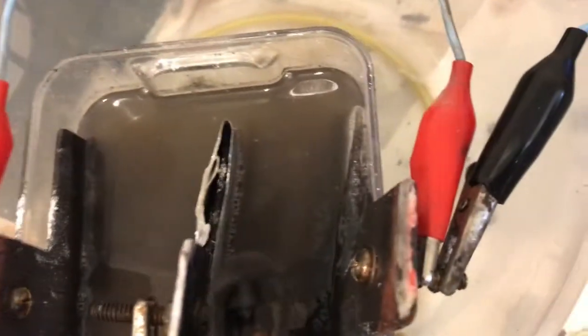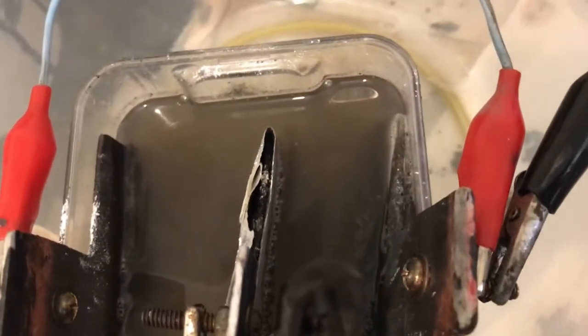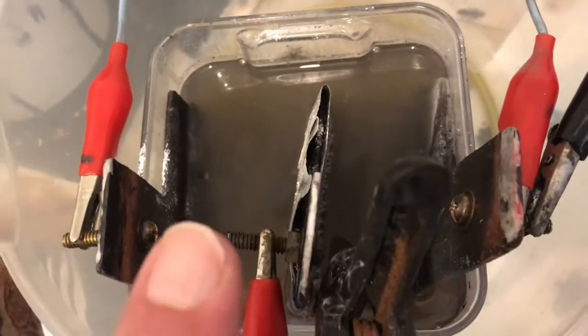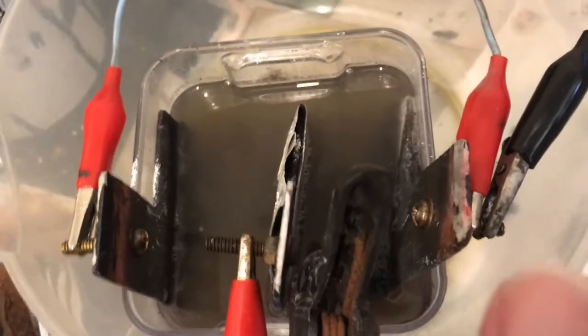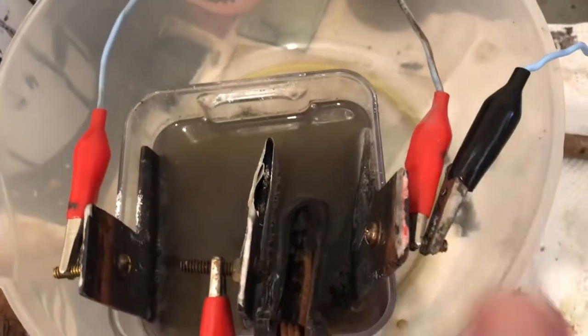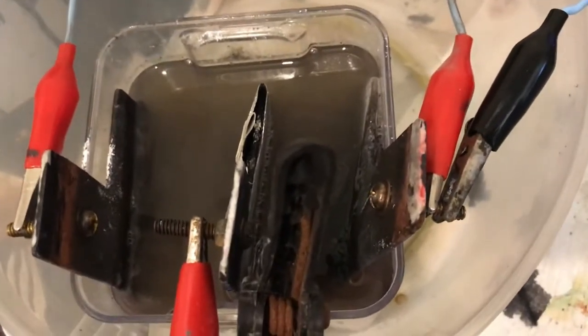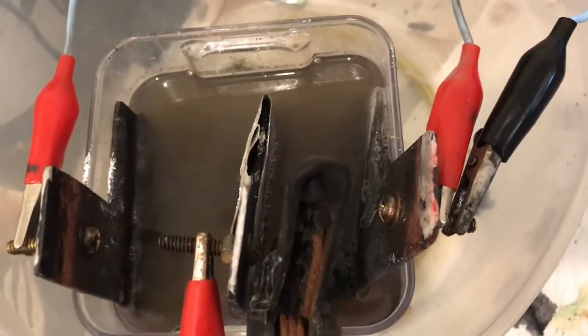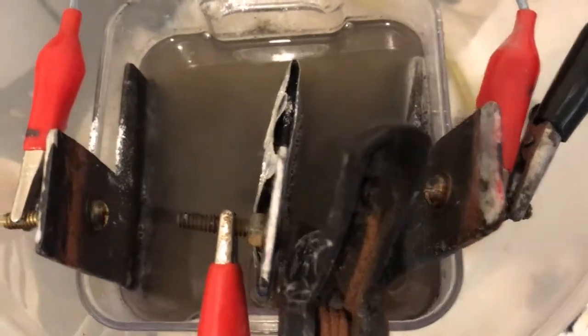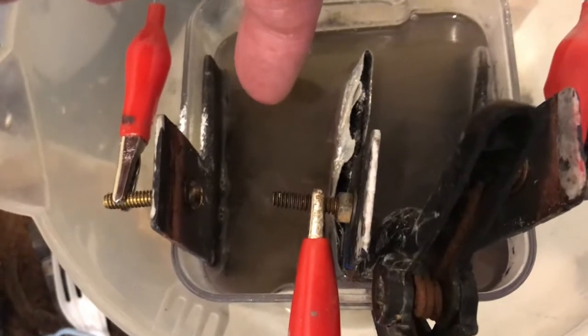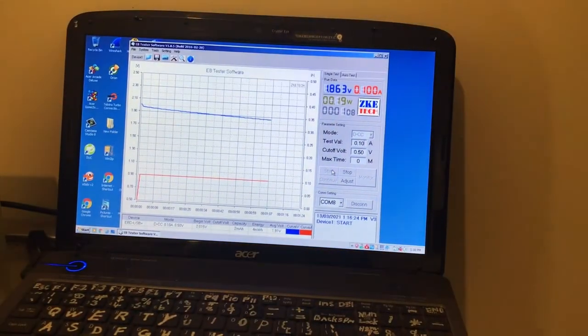The plates are spaced pretty far apart. We only probably need like 10 mil or a finger distance between each cell. They would need some sort of spacer to hold them in place. That will eliminate dendrites touching the positive, because after 6 hours we've only got like 6 millimeters of growth hanging off of the side, and if you don't stick too much zinc in there you're not going to get any further than 6 millimeters.